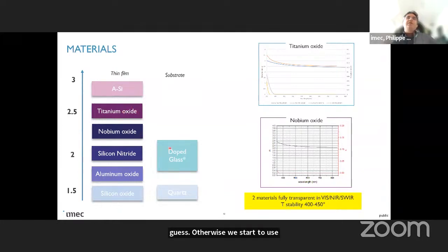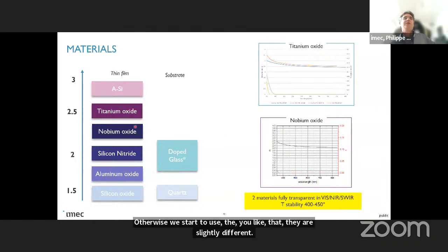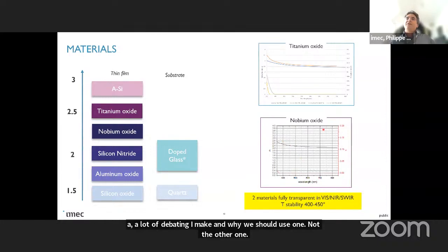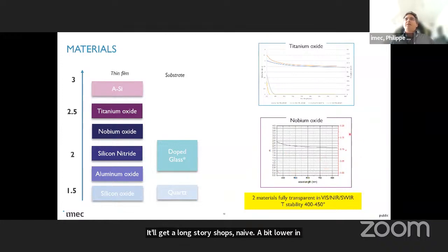They are slightly different. There is perpetually a lot of debate in Imec on why we should use one and not the other. To cut a long story short, niobium oxide might be a bit lower in index, but actually is much more stable when it comes to temperature. And titanium oxide can still buy you some performance if it's processed in the right manner.